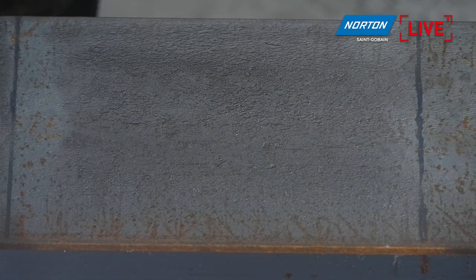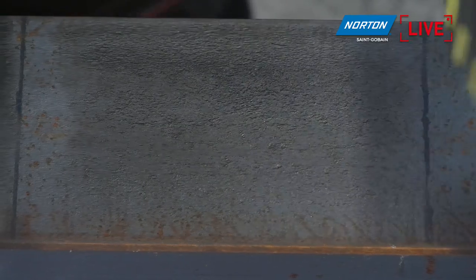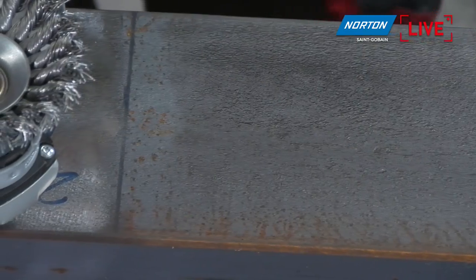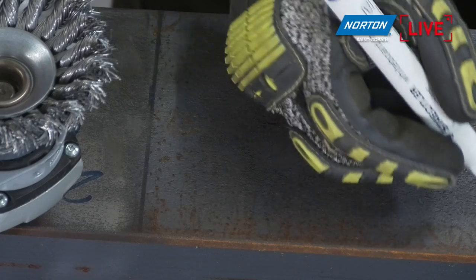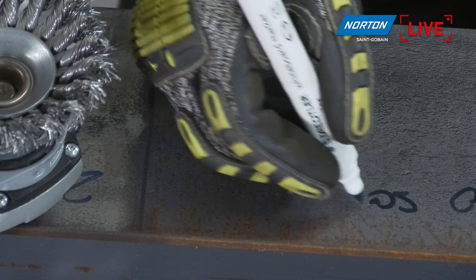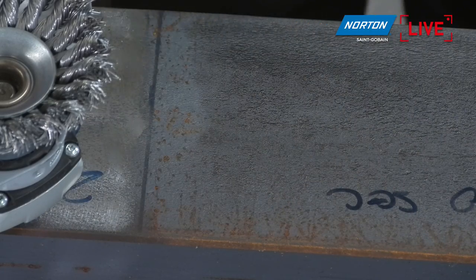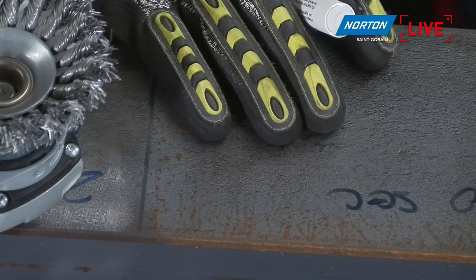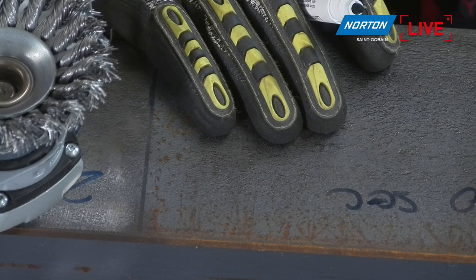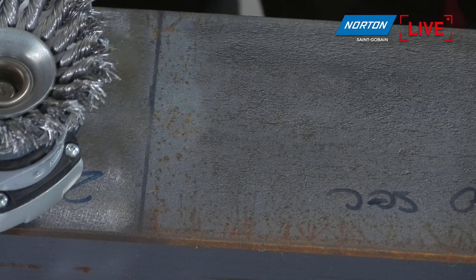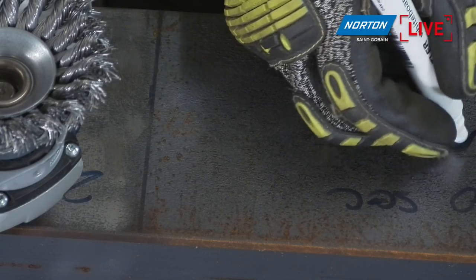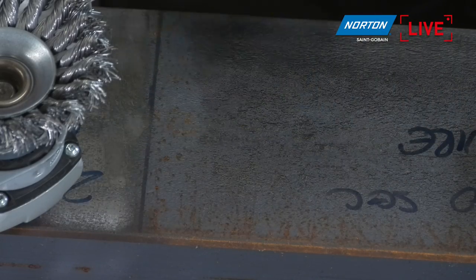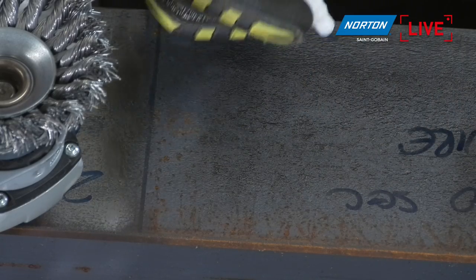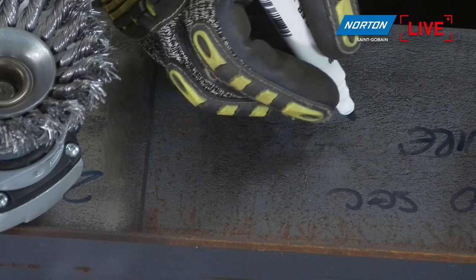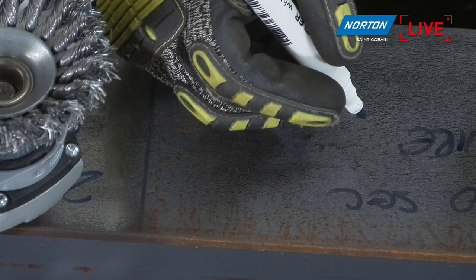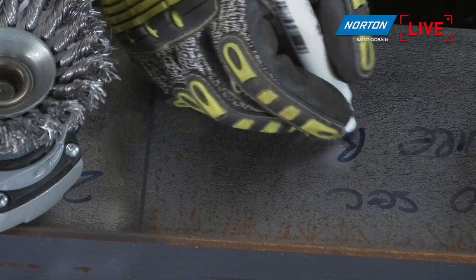That was 50 seconds in total doing that. So I gave it the same amount of time as the grinder disc in step one. But really, for me, it's not done the job on this material. I think this is too thick and too tough for the wire brushes to actually get through that hard skin. So yeah, it will do a job on thinner paint, thinner corrosion, but not on this heavy duty. It just didn't quite get there.